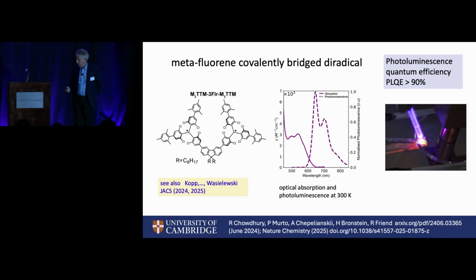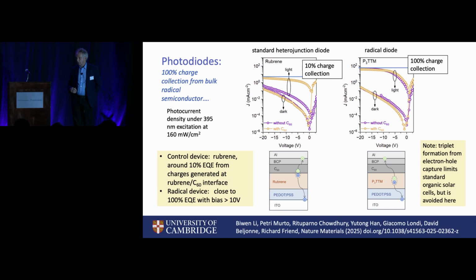If we go to our bulk TTM radical, we can extract all the charges. We have 100% quantum yield for charge collection. We need a bit of field to do it, but we've now managed to throw away the heterojunction, the donor-acceptor interface, which has underpinned everything we know about excitonic photovoltaics. I'm not saying that's going to tomorrow transform how we make solar cells, but it is certainly another avenue to explore where we've just played around with spin.